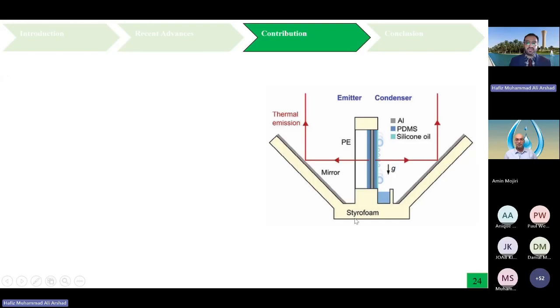So that is why. And in the total system, you see that we have styrofoam in order to insulate the system from the surroundings. If the ambient temperatures are already low, this is going to help increase the radiative air water harvesting. But if the ambient temperature is really high, which is generally the case in Middle Eastern countries, mostly during the summertime, it becomes really challenging to isolate the system from the thermal mass. If we can do that, then more air water harvesting can be achieved. I hope that this answers the question.